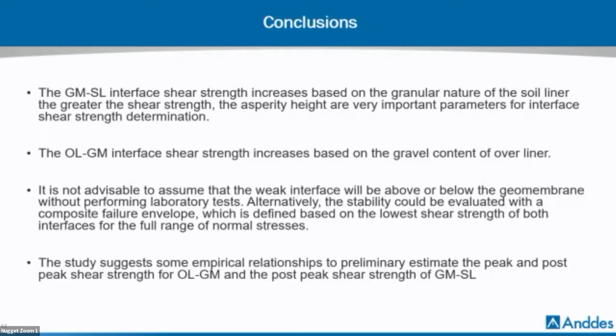Alternatively, the stability could be evaluated with a composite failure envelope, which is defined based on the lowest shear strength of both interfaces, for the full range of the normal stresses. These studies suggest some empirical relationships to preliminarily estimate the peak and post-peak shear strength for overliner with geomembrane, and for the interface with geomembrane soil liner, we propose a post-peak relationship.